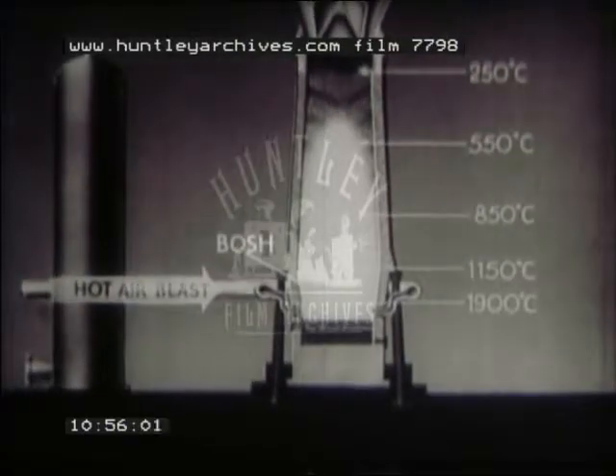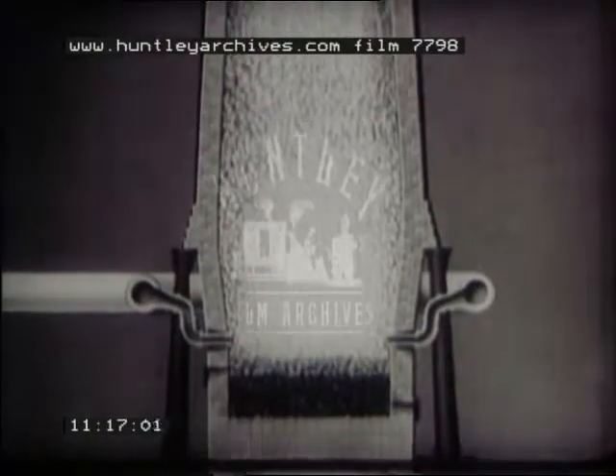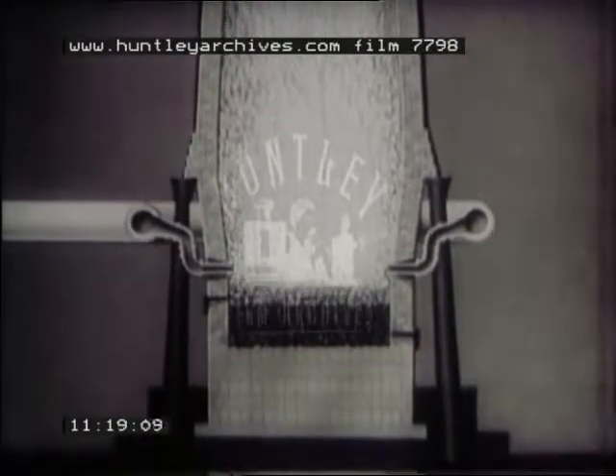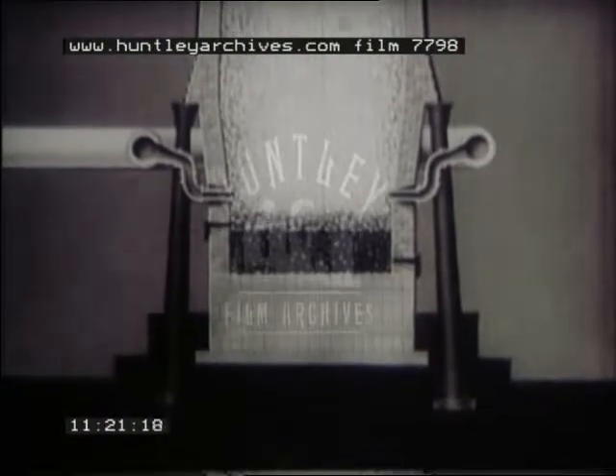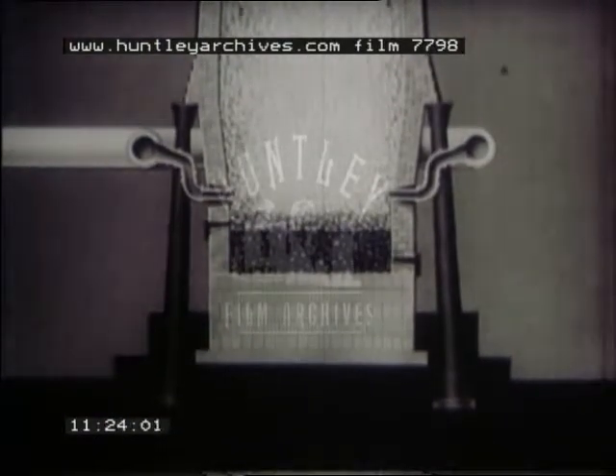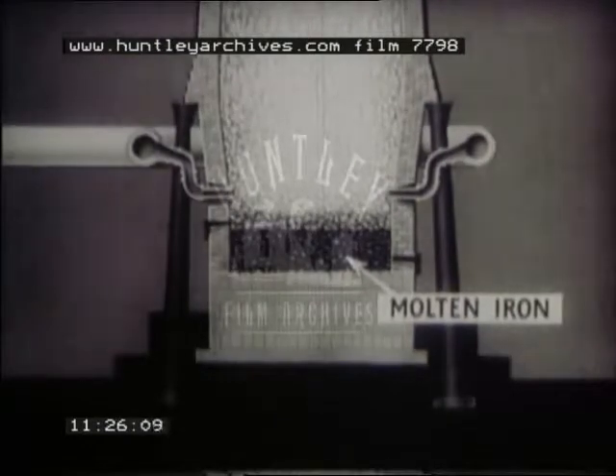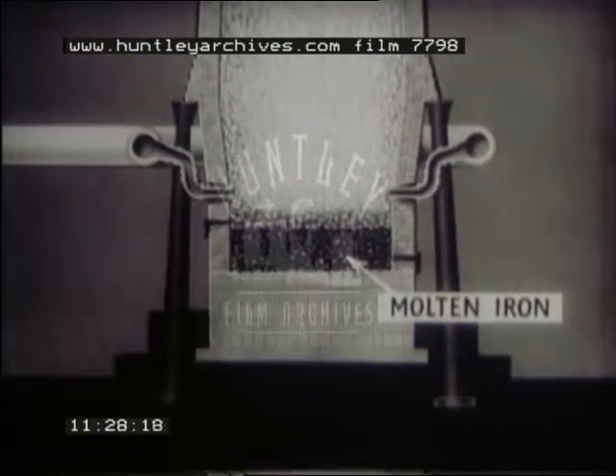You can see there's a two-way flow inside the furnace. The gases travel upwards, getting cooler as they give up their heat to the burden. The burden travels downward, getting hotter as it picks up heat from the gases. As the burden gets hotter, it eventually reaches a temperature at which the chemical reactions of smelting can start, and molten metal and slag begin to collect in the hearth. By the way, the hearth doesn't only contain liquid. As we show, it's filled with lumps of unburned coke, which hold up the rest of the burden.